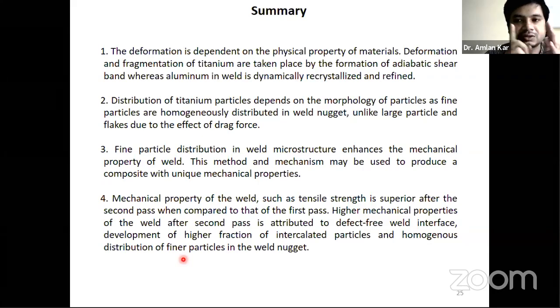So actually the tool and the titanium are subjected to shear deformation at a low temperature, and that led to the fragmentation and dynamic recrystallization. The mechanism which is involved in leading to such microstructural development is adiabatic shear band formation. And why is titanium subjected to adiabatic shear bands? Because it has a lower number of slip systems and lower thermal conductivity, and that leads to adiabatic shear